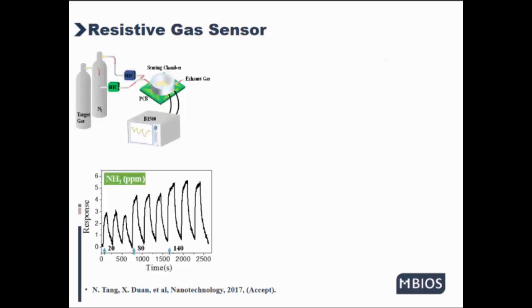And to test the gas sensing performance of the resistive gas sensor, the sensor was used to detect different concentrations of ammonia. And the responses of the resistive gas sensor have no significant changes after exposure to the same concentration of ammonia, implying the good repeatability of the resistive gas sensor.